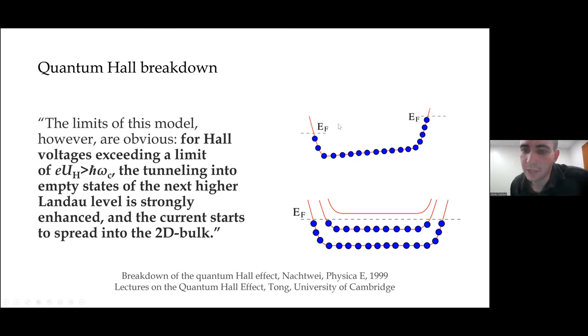And if that difference becomes large enough, you'll eventually populate the next Chern band, the next Landau level, with the local bias potential. And once you hit that regime, you'll start populating electrons in the conduction band, and you'll have metallic behavior, or you'll have electrons spilling into the bulk. So I think we can understand something like that as going on in this quantum anomalous Hall effect.